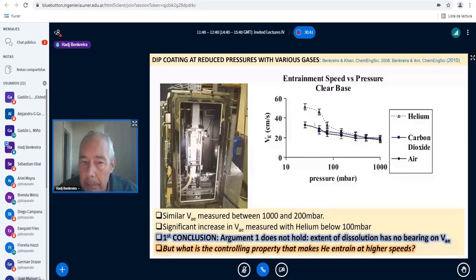Look at helium, it's much higher. For air and CO2, it's pretty much the same, but it's still increasing. So immediately, argument number one does not hold. The extent of dissolution has no bearing on the gas entrainment velocity. Gas entrainment is a sudden catastrophic event. It has nothing to do with the dissolution of the gas into the fluid.